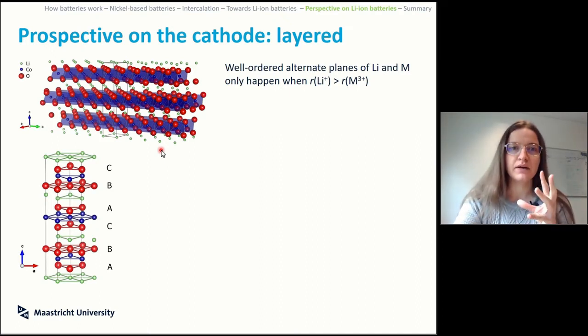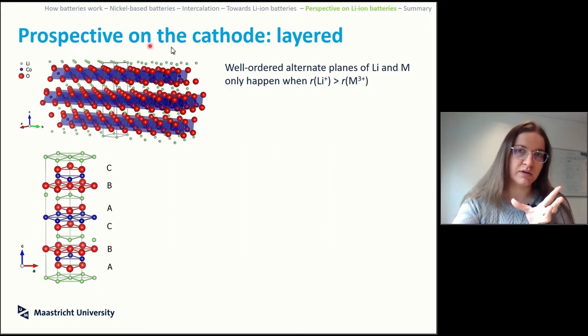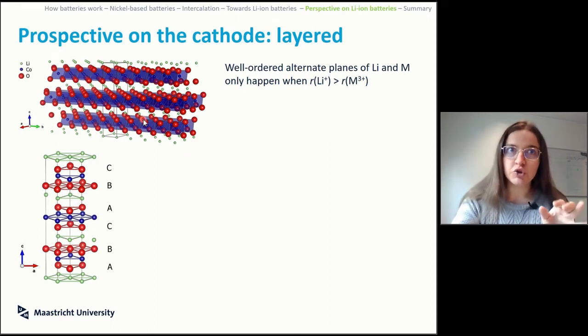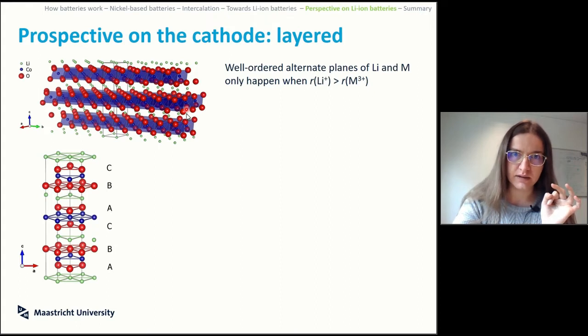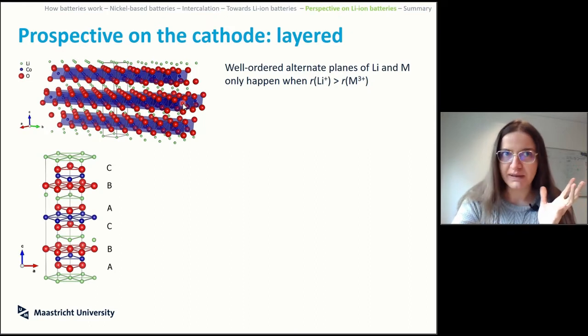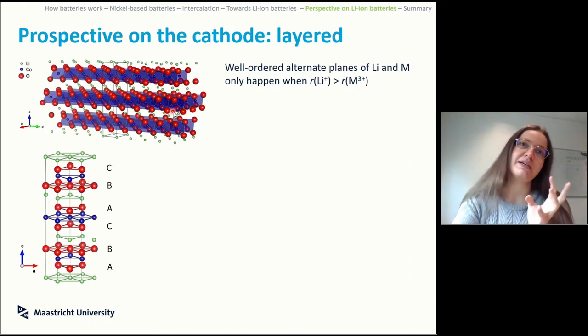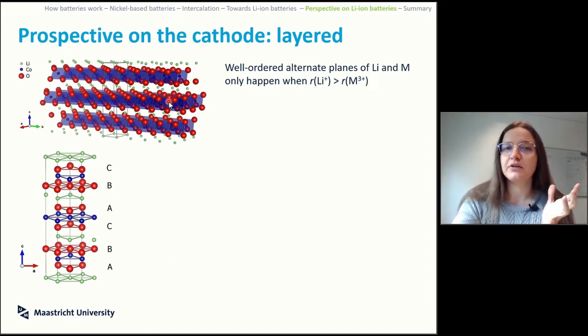Now, as we were discussing before, the first thing that you need here is that the planes in the structure, if you use the so-called O3 structure, which is this thing with layers, you want the order to be as optimal as possible. So your octahedral cation, which is your transition metal cation, must not like the same octahedral position that the lithium will occupy.